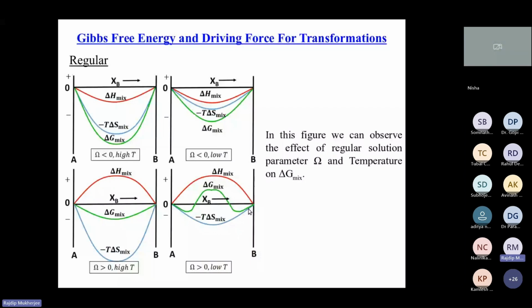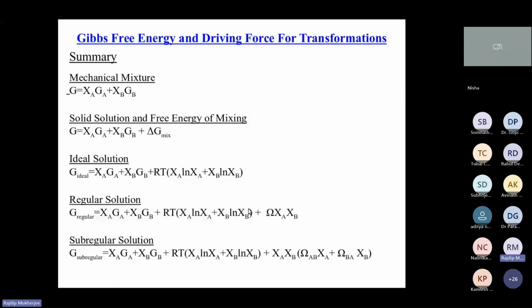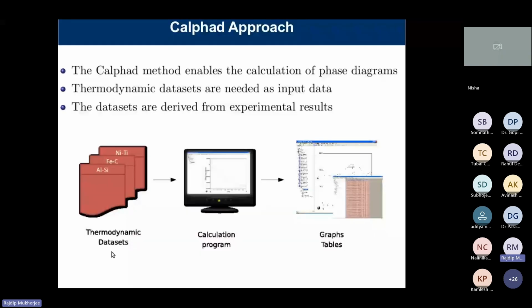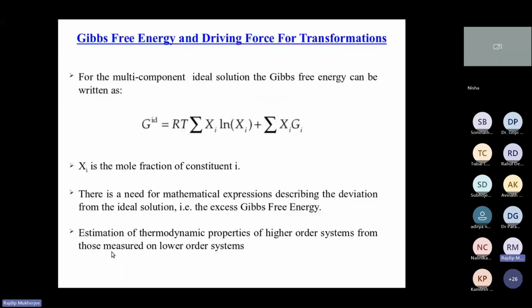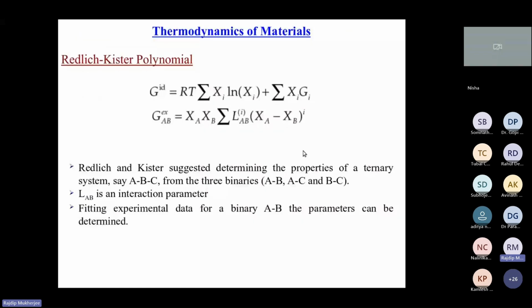So finally, we have defined models. You can read about them: the mechanical mixture, solid solution models for free energy of mixing, ideal solution, regular solution, sub-regular solution. But ultimately, we need more complicated polynomials which can fit a free energy, also known as the Redlich-Kister polynomial, where you have a multi-component and multi-phase system, right? So not only binary or ternary. So in CALPHAD we basically have this kind of polynomials where you can get the mixing energy and free energy, right?